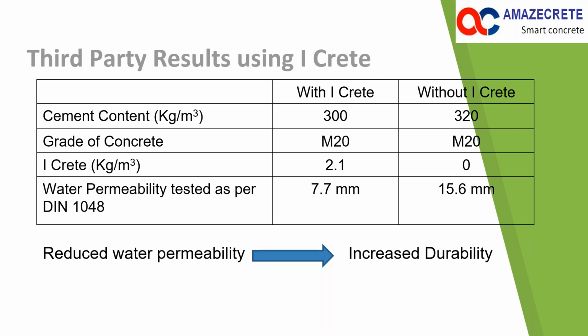So it always in a way defies the normal acceptable water cement ratio law, which says that as the water cement ratio goes up, strength reduces, or as the water cement ratio reduces, strength goes up. So here, even when the water cement ratio is slightly up compared to control, using iCrete you have equal or better strengths, and better durability, better permeability and other properties. Next one.